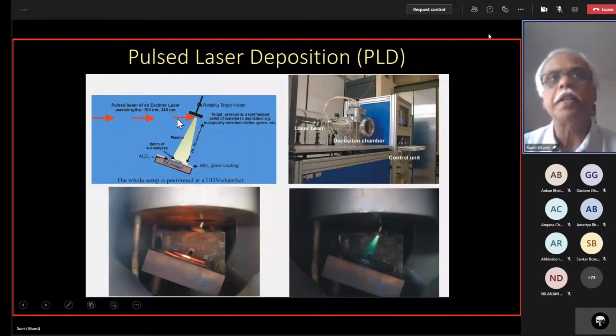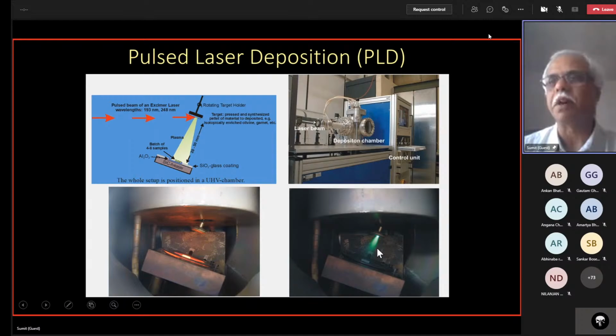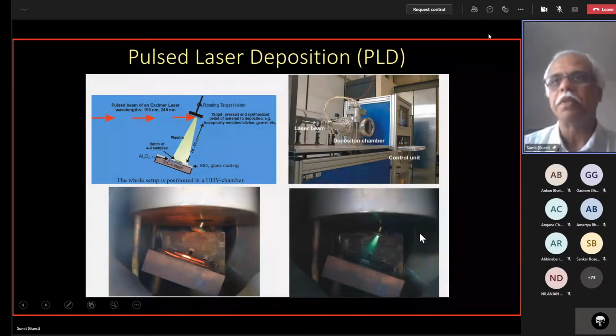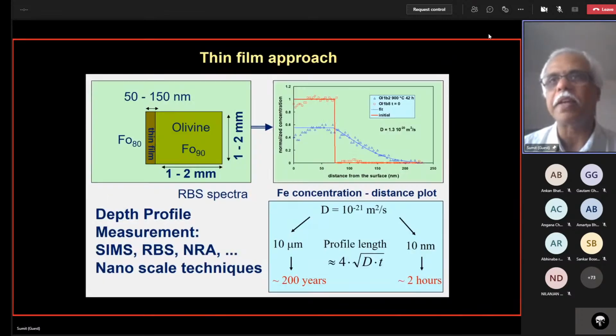So once you turn on the laser, what happens is this here. This is now an olivine crystal of a particular composition that is being targeted with the laser. This green thing is olivine plasma. So the magnesium, iron, silicon in olivine has been converted to an ionized state in a gas, and this then deposits that film onto whatever surface you have here. So what that looks like is something like this.